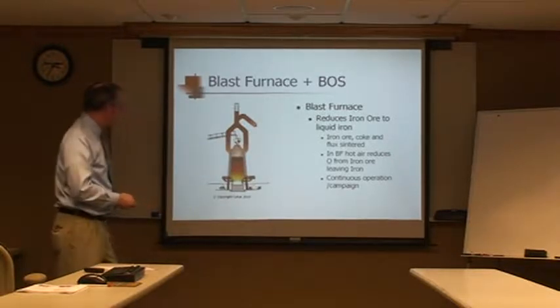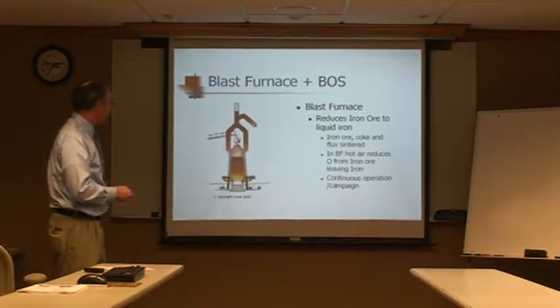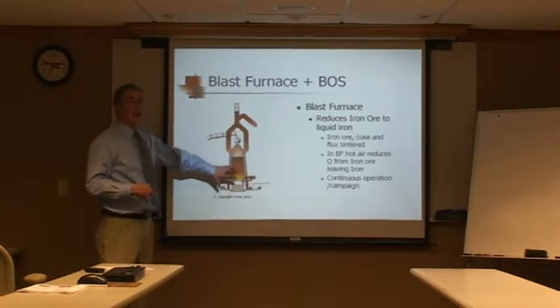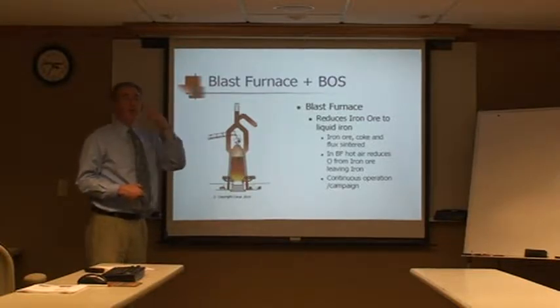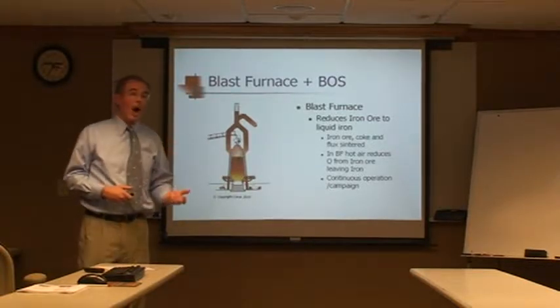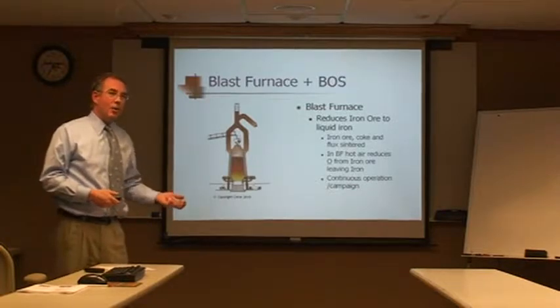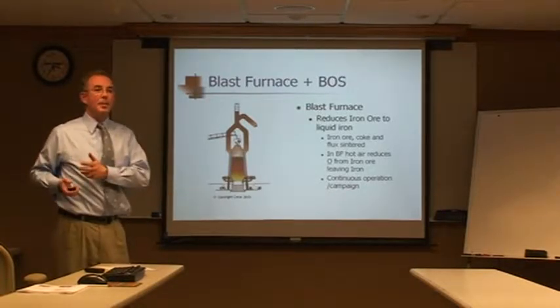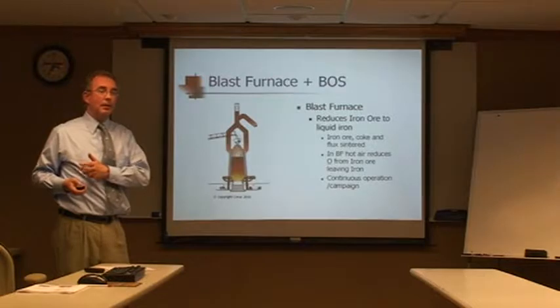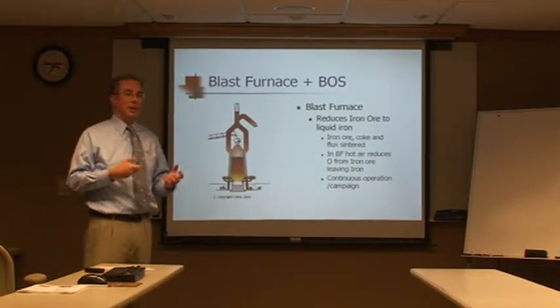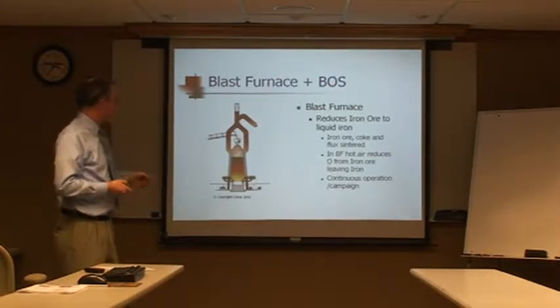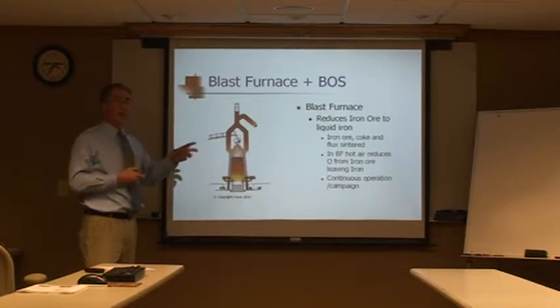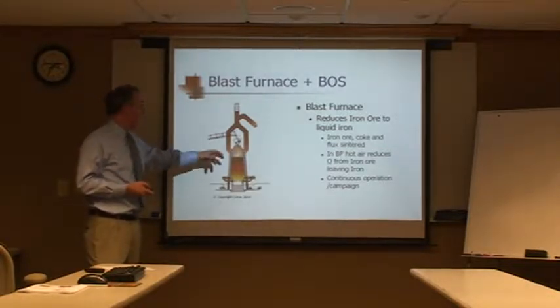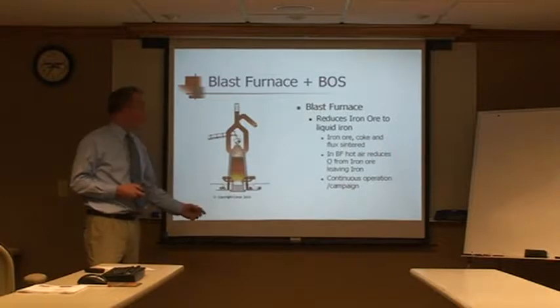At the bottom, there's very hot air getting blown in here. And this hot air blows up through here, and as this falls, this begins to heat. And as that gets hotter and hotter, the carbon reacts with the oxygen in the iron ore to tie up and make carbon monoxide gas, leaving just the iron. So it's a chemical reaction: the carbon and the oxygen react, and then it leaves pure iron. It's a continuous operation.